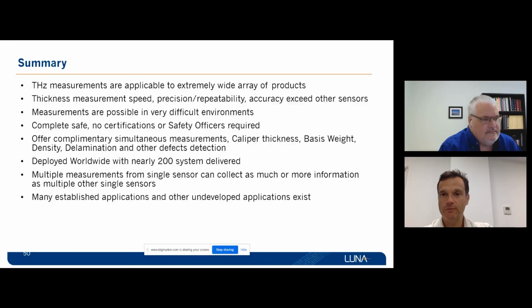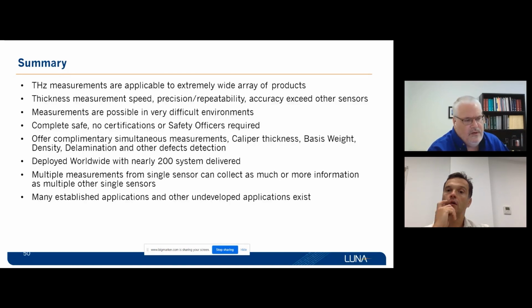Sure. Do you want to take this last one from Shyam Sunder? He wants to know what the typical beam diameter in your case is. As I said, that depends on how you tune your frequency operating range and the focusing lens you use. But that's anywhere from 250 microns, more typically between 1 and 2.5, sometimes 5 millimeters, depending on the sensor you want. For a thickness sensor, we typically use a somewhat larger beam to average out over a slightly larger area. And for imaging, we try to get the beam tight for small features. Fantastic, thanks.